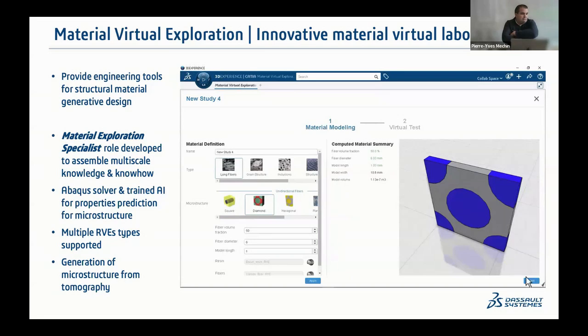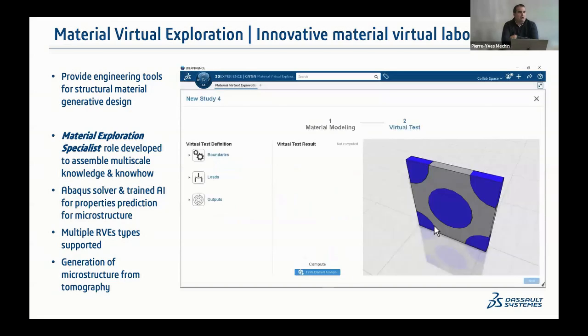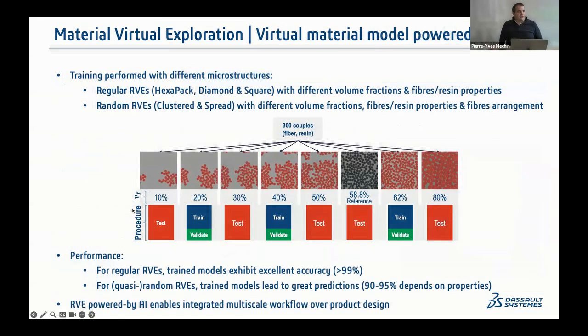We're able to deal with different microstructures again, and this is quite an interactive new app where we model the complexity of the microstructures. For the AI model, we've been using some TMN models, which are quite efficient for material multiscale prediction, where we balance test and training. So we train for different volume fractions, and we run some tests to validate how it works. It responds pretty well to the variation of the volume fraction, of course.